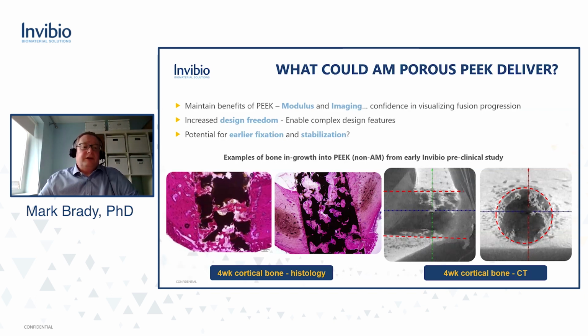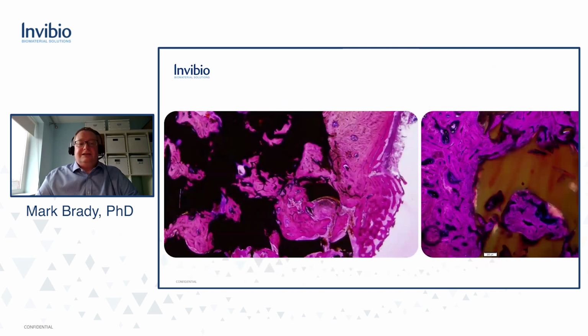We know from some previous studies that bone will grow into porous PEEK structures, both from our own studies here at Invibio and from some of those technologies that have now gone on to be commercialized. In some of those studies, it was shown that the addition of a thin titanium coating resulted in similar degrees of bone ingrowth, but no increase in implant fixation, suggesting that it's really the structure rather than the chemistry that's the driving force.